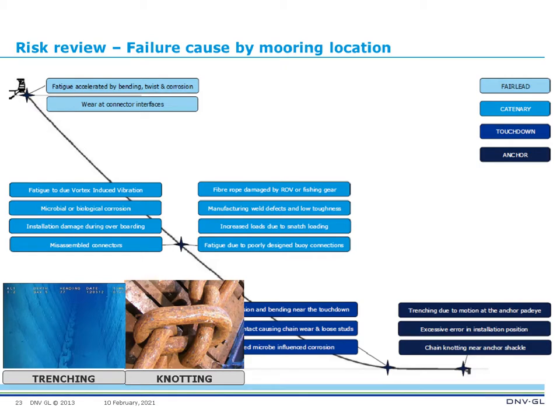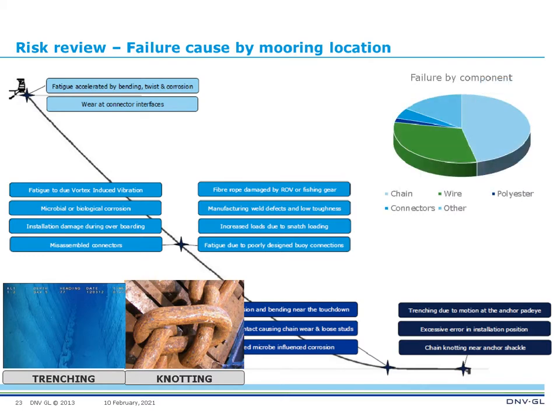Closer to the anchor, we have observed trenching and knotting of the anchor chain, which impacts the load path, and hence the calculated loading from the mooring analysis may not be valid. Most failures are due to chain, then wire, but this may also be due to the more extensive use of these components.